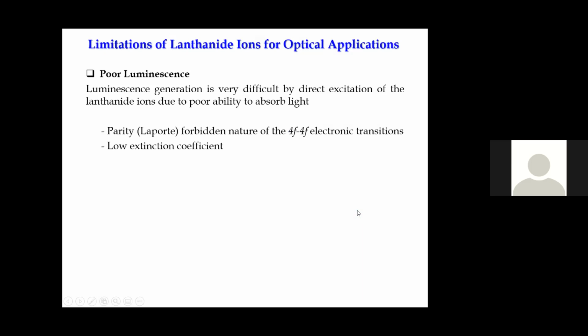The problem so far is that with any metal-based nanoparticles, the luminescence is very weak. The reason is what we call a selection rule in photophysical properties. One selection rule is that excitation between the same orbitals, 4f to 4f orbitals in this case, is forbidden by the selection rules. We call it the parity rule or the Laporte rule. Bottom line is they are not good.